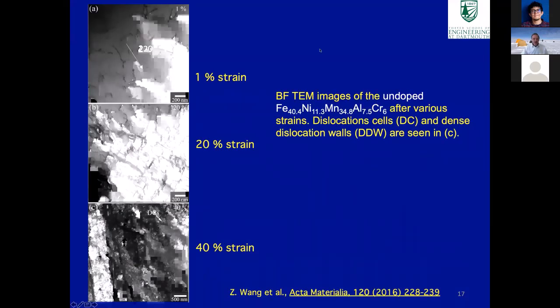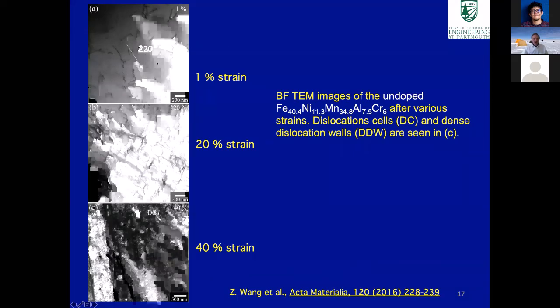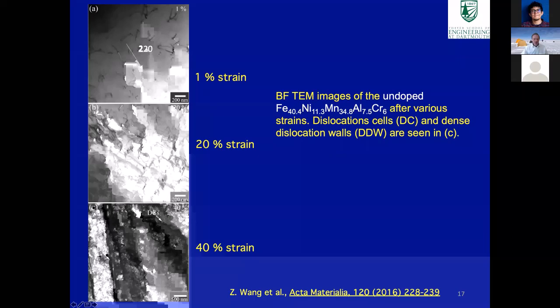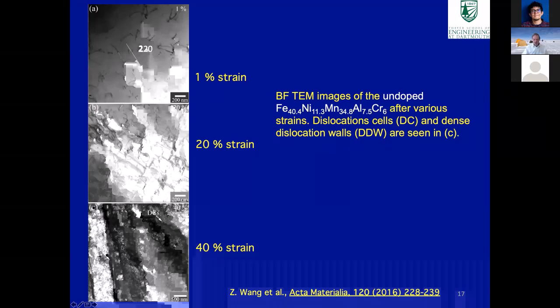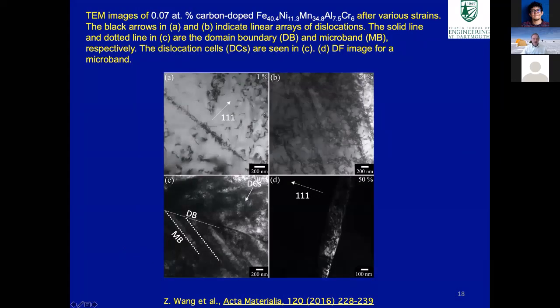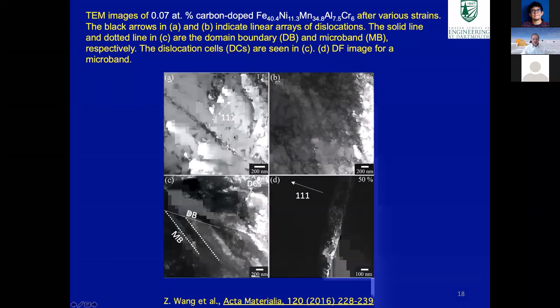We looked at dislocation structures, and this is the material without carbon at different strains. You can see a pretty wavy sort of dislocation structure. As you get to very high strains, you get dislocation cells forming and these dense dislocation walls. Once you add a little bit of carbon to the material, even the smallest amount we added, all of a sudden you start to get much more planar slip in the material. And at very high strains, you get these microbands forming in the material.